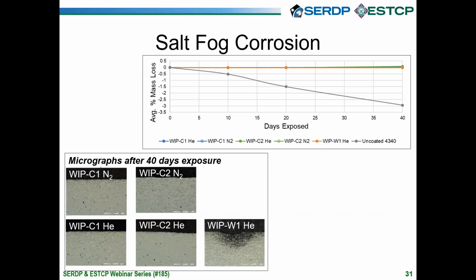However, when we look at the micrographs of those samples after 40 days, we did see that the WIP W1 coating had significant porosity that had formed, which would indicate that the W1 would not have great corrosion resistance and may need additional protection. However, all the other WIP C coatings did not have any pitting after 40 days exposure.